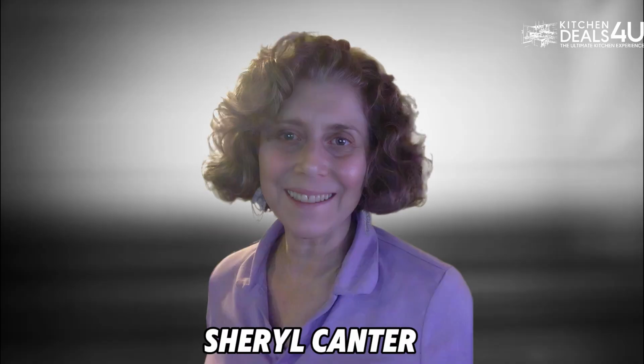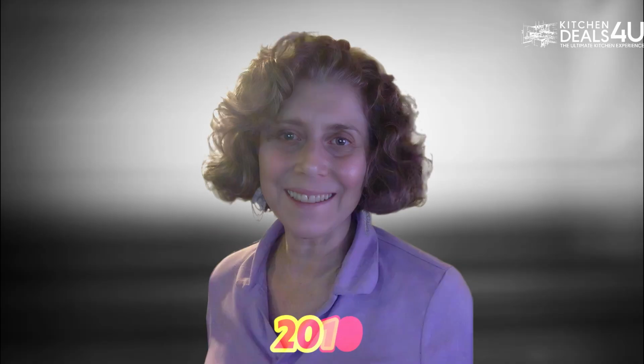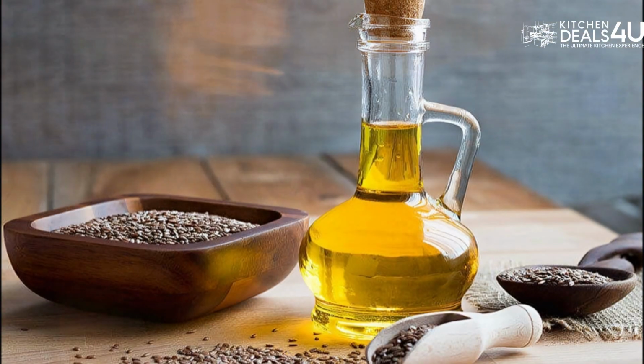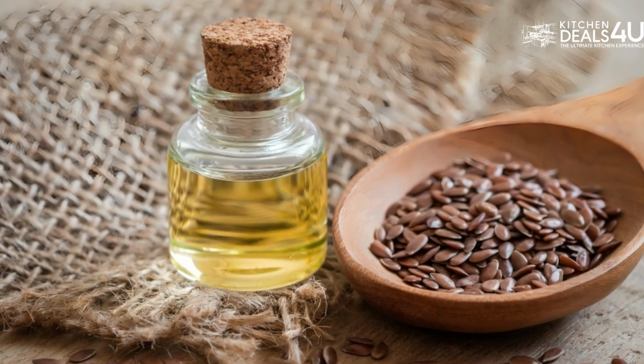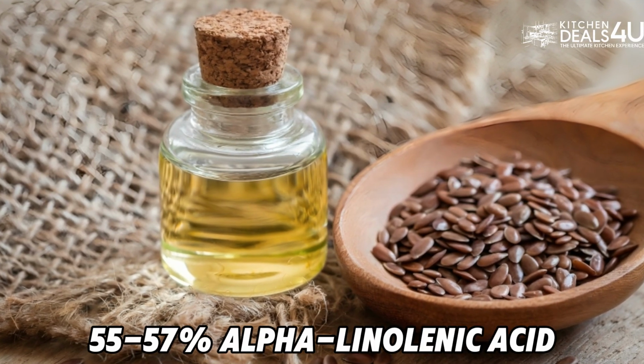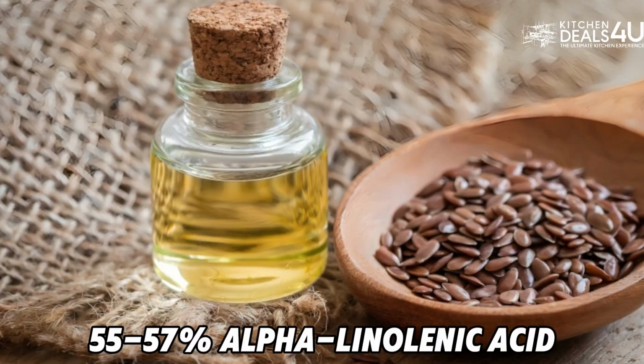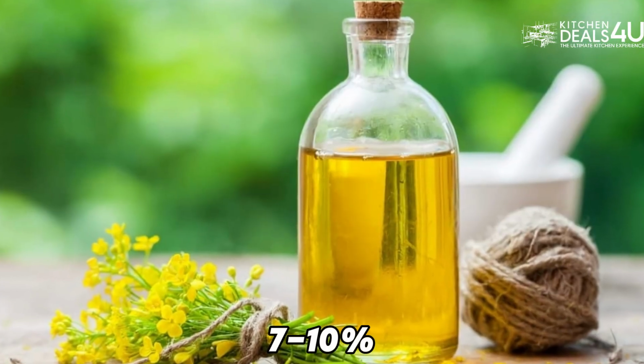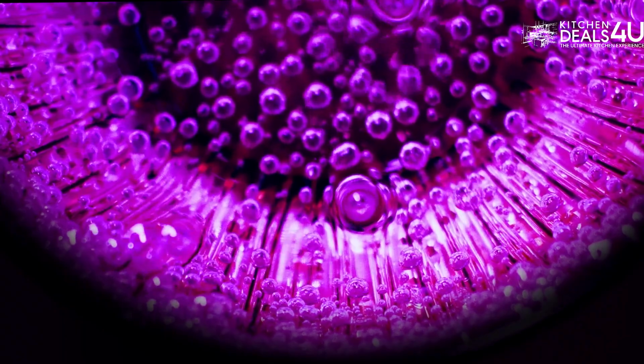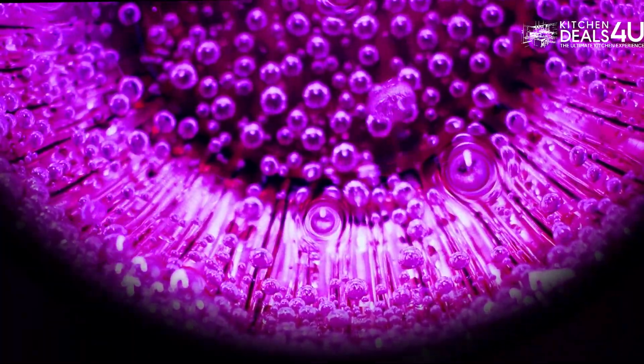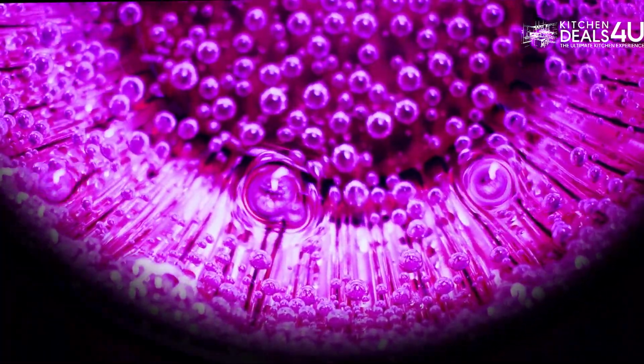Method 2, the flaxseed oil revolution. Food scientist Sheryl Canter changed cast iron care forever back in 2010, showing that flaxseed oil creates the hardest polymerized coating of any common oil. Flaxseed oil contains 55 to 57% alpha-linolenic acid, compared to just 7 to 10% in canola oil. Those molecular double bonds allow tight cross-linking, creating a coating almost as hard as plastic.